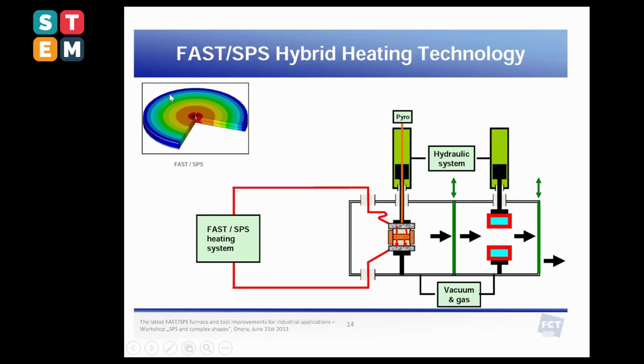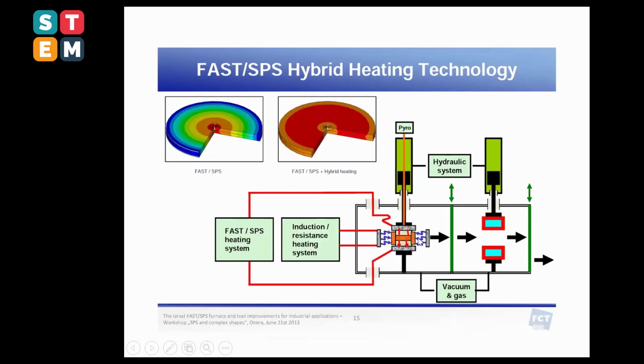And to avoid this, they propose what they call here the SPS hybrid heating technology. That means they add inside the machine some additional induction resistance heating system, as I clearly show here. And they were able to produce such large samples without any thermal gradient.